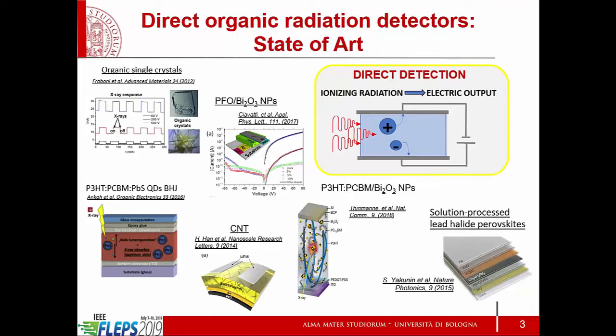There are examples, but very recent, of organic material used as direct radiation detectors, because historically, organic materials have been used for the indirect detection. So they were used for scintillators, and now we know there's quite a lot on organic photodiodes based on printed transistors and OPDs. Now what we want to do is to use organic small molecule materials to directly detect the radiation. There are examples of blends between polymers, bulk heterojunctions, with nanoparticles or structures added that have a high Z to increase the absorption of the desired radiation in a very thin layer.